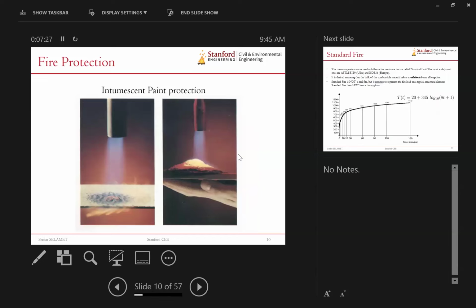This one pretty much dominates the market at this point, which is called intumescent paint protection. It's not a recent development, but it's been here for maybe 20 to 30 years. And it is a paint. It's very thin. You can think of this as a corrosion paint that you apply on steel. But this paint has a special property. It swells when it's exposed to high temperatures. So when it swells, its thickness increases, and it is already a very good material for fire protection. Again, it basically makes sure that the heat doesn't travel as fast inside the steel.